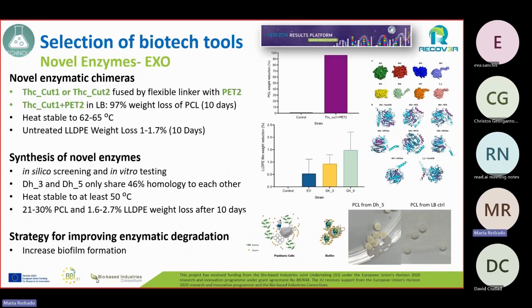As for the novel enzymes, which are the other exo part, we produced novel enzymatic chimeras by fusing the cutinase with PET2, and those were capable of reducing the weight of polyesters. They have polyesterase activity. They reduce the weight of polycaprolactone by up to 97% in 10 days, and it is interesting that they are also heat stable, which is a good quality for enzymes for polymer degradation. They are also capable of degrading LDPE with a weight loss of 1 to 1.7 in 10 days.